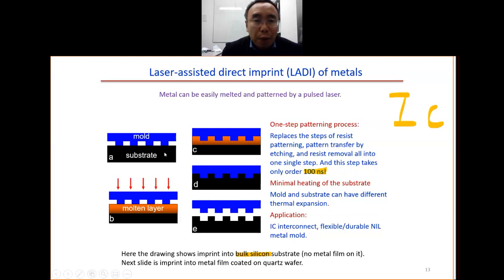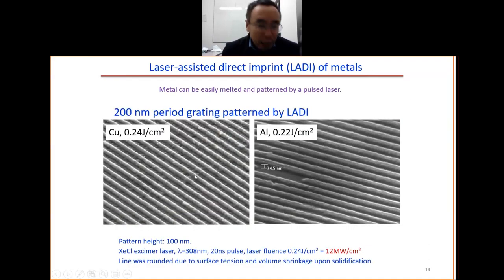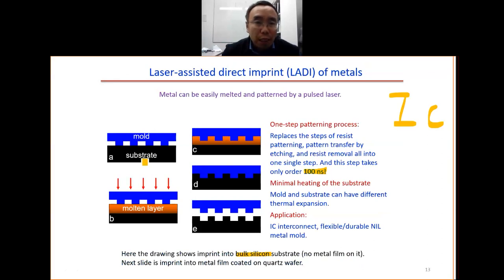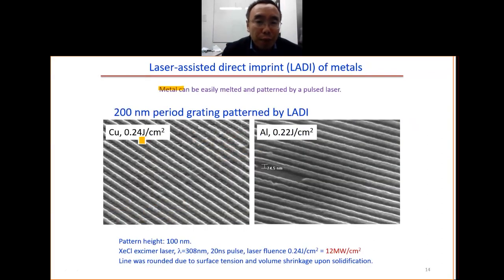So we can do a similar process using metal. The idea is simple. You coat the metal film on top of the silicon substrate. Then you do the same process. So the metal can be melted by the laser pulse. Here in this case, we use the xenon chloride laser. This is the excimer laser.